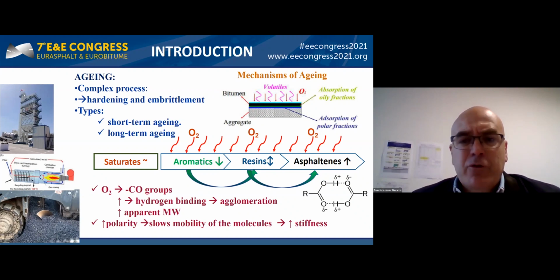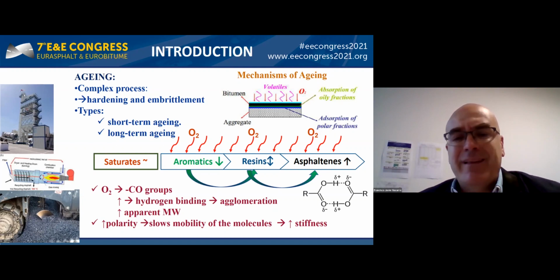However, the main one involved is the oxidative aging that causes a strong modification in the chemical composition of bitumen. During oxidation, new carbonyl groups are formed and the polarity of the molecules increases. Thus, whereas saturates remain relatively unaffected, aromatics are transformed into resins and resins into asphaltenes. Therefore, bitumen oxidative aging favors electrostatic interaction by hydrogen bonding of the molecules, a fact that contributes to the agglomeration of the asphaltene structure and leads to the embrittlement of the pavement.